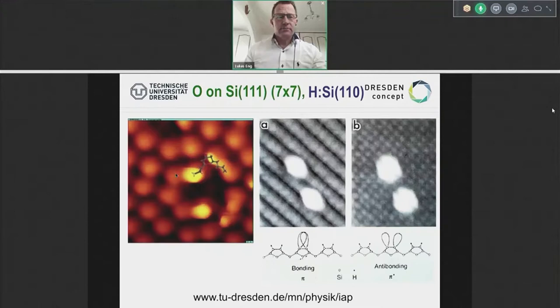What is really the holy grail here? The right example shows you we have hydrogen adsorbed to silicon. This is a silicon 110 surface. And changing the bias of your sample from positive to negative shows you that you can really go from bonding sites, shown here in the cartoon, to antibonding sites. That's exactly pi star orbitals. And I hope you can see on your projection that there's really a dashed line in between here. You see much better in the background, because you can resolve the silicon atoms 110. Here you can't. These are rows 110, depending on the bias.